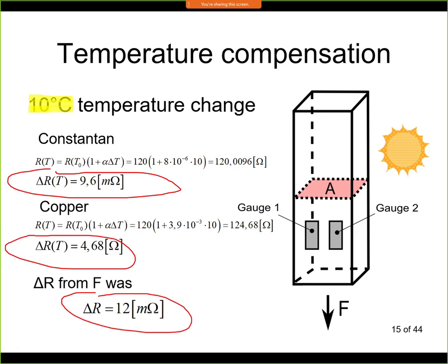at all. So we can see that even if we use the Constantan for the strain gauge without temperature compensation, we will run into big trouble, because this value by only a 10 centigrade change is very significant, and it has almost the same size as the value created by force. And you can basically not distinguish if the force has changed or if the temperature has changed, unless you measure the temperature, for example, or unless you compensate for the temperature changes.